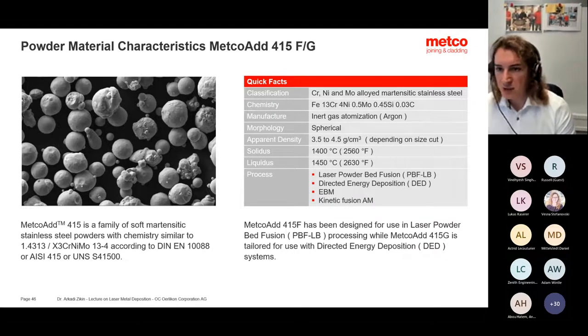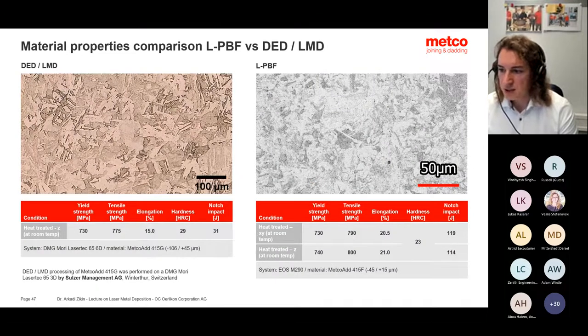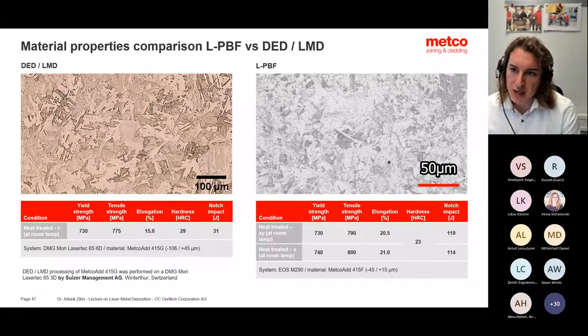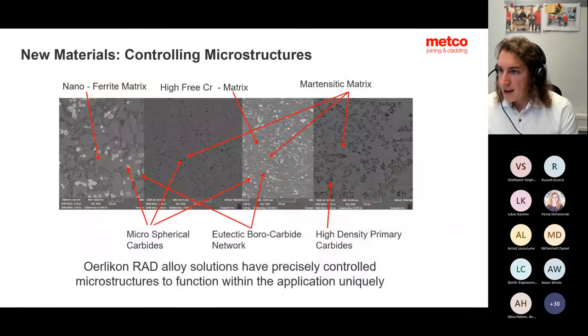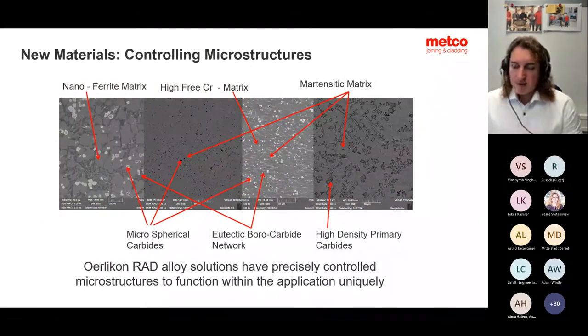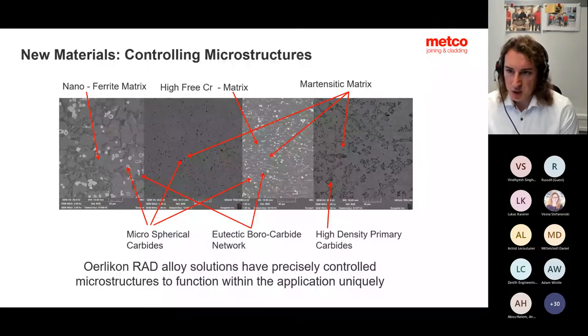And we have a product for powder bed fusion and also for DED. And what is most important is that your strength and yield values are more or less comparable to the bulk, and you also get an increased hardness, which might have advantages in terms of wear protection. What is also very important if you develop new materials is that you have full control over the microstructure features. And in my opinion, this is also a new world in terms of materials development.